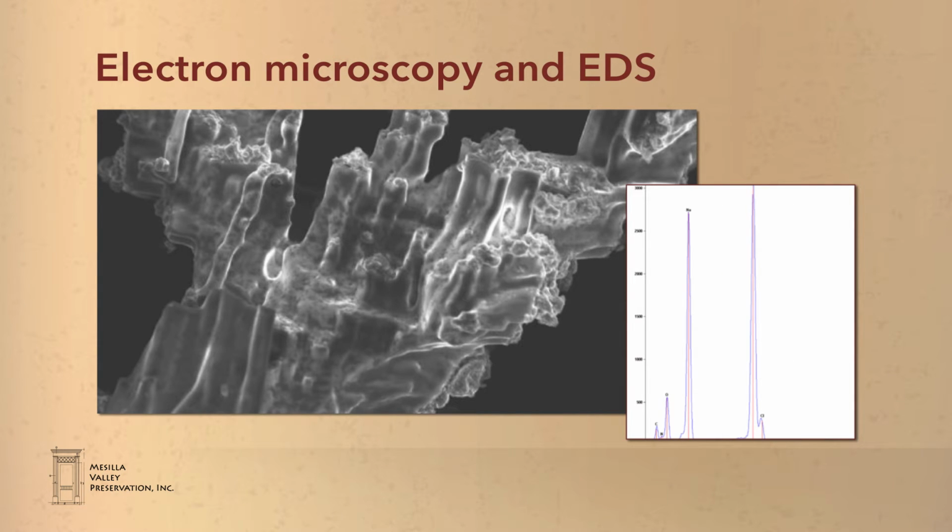where they grew. Here is the same salt crystal when viewed by an electron microscope. Notice the root-like structure and the little structures that look like stalagmites. As described by the scientific literature, as the crystal grows, the larger portion of the crystal draws moisture toward it. That salt-laden moisture then contributes to the growth at the large end of the crystal. The crystal eventually exerts enormous crystallization pressures on the wall of the microscopic pore system, and ultimately fractures the adobe.